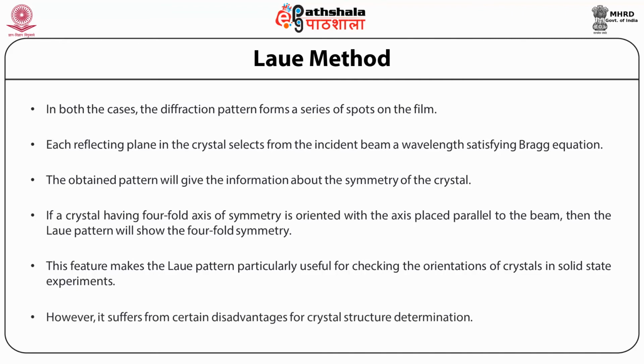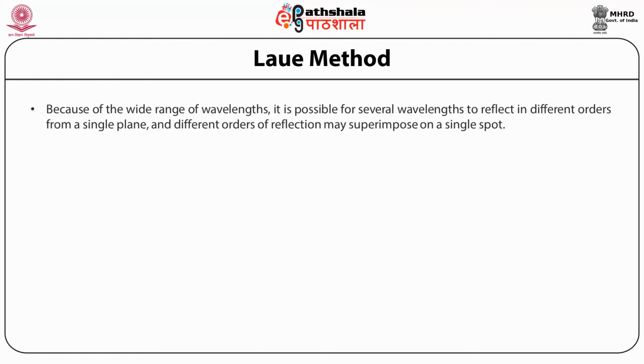However, it suffers from certain disadvantages for crystal structure determination. Because of the wide range of wavelengths, it is possible for several wavelengths to reflect in different orders from a single plane, and different orders of reflection may superimpose on a single spot.